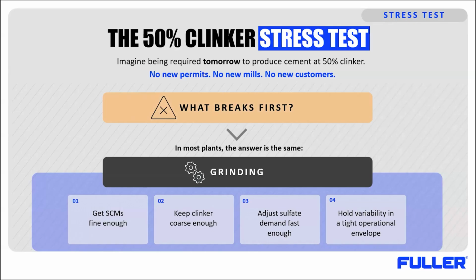So the SCMs must be fine enough to contribute to the strength and reactivity. At the same time, the clinker should not be overground because that can waste energy and increase water demand. The sulfate balance also becomes more sensitive, and the whole system must stay inside a tight quality envelope. So 50% clinker is not just a formulation target, it's a full system capability test, and it tests grinding, drying, classification, blending, sulfate control, quality control speed, and process response.